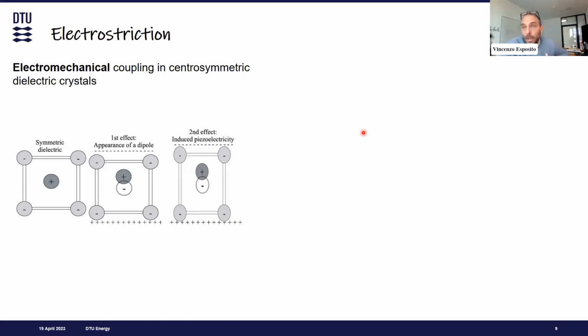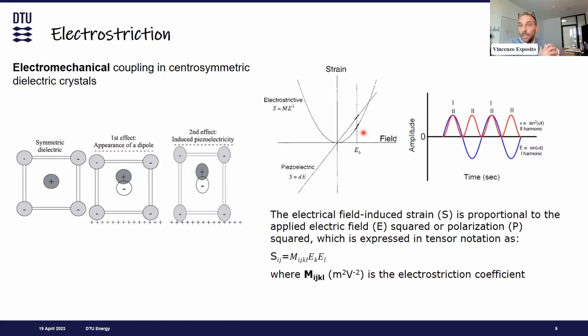We cannot, unfortunately, get the other function typical of piezoelectrics, the direct piezoelectric effect, where, by applying a strain, we get some electrical current. However, the electrostriction itself is pretty large. Another difference with piezoelectricity is that electrostriction follows a quadratic law. That means it follows this parabola, and the signal is always positive, exactly because it's a quadratic law.